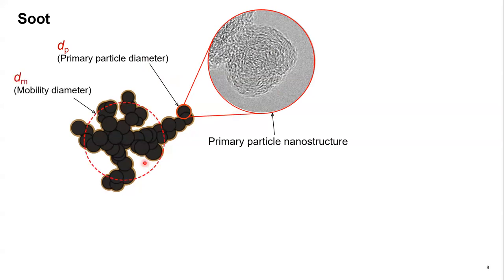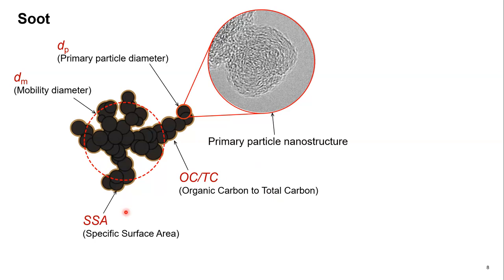We also need to define the size of the entire agglomerate, and throughout this presentation, we will be using the mobility diameter. As we saw in the last slide, the mobility diameter determines how these particles deposit in our lungs, and also how they transport through the atmosphere. From a chemical perspective, we can quantify the particles with the organic carbon to total carbon ratio, or the OC/TC ratio. And this is basically a measure of the amount of volatile and semi-volatile compounds to the total amount of carbon in the particle. And the last thing is the specific surface area, which I've mentioned a few times before.